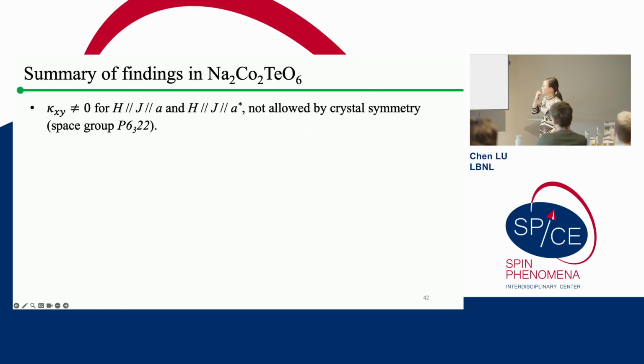At this point, I want to give a very short summary of what we found so far for the planar thermal Hall effect in a Kitaev candidate material, sodium cobalt telluride. First of all, we found a non-zero planar thermal Hall effect signal with both field and current parallel to a high symmetry principal axis. And if you check the global space group, you will find that along both of these 2 directions, they have a C2 rotational symmetry, which means theoretically it should not be allowed by crystal symmetry.